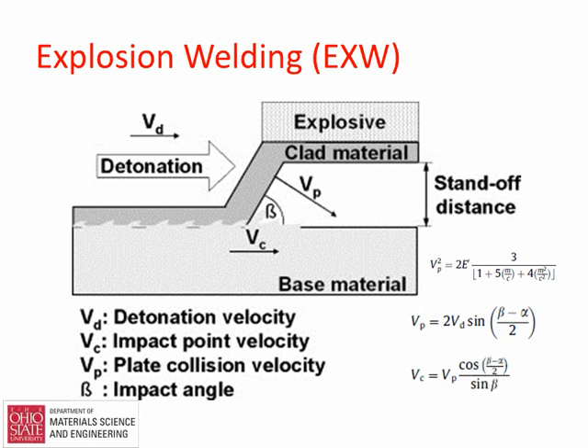And so basically, different explosives have different Gurney energies. So based on a specific parameter of the mass ratio, M is the mass of the plate, C is the mass of the explosive, we can actually predict the velocity of a plate. The velocity of an explosive: every explosive has a characteristic detonation velocity.